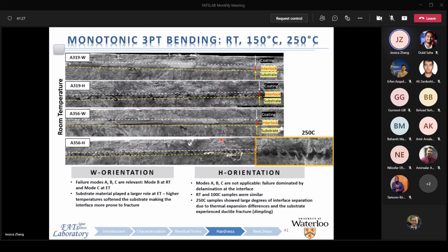And generally, when we look at our flat samples, this is an image at room temperature. Generally, a combination of delamination and coating breakage is what we saw here, so modes B and C. And more breakage was seen at higher temperatures. The higher temperatures also resulted in more breakage specifically at the interface. It was more prone to fracture.